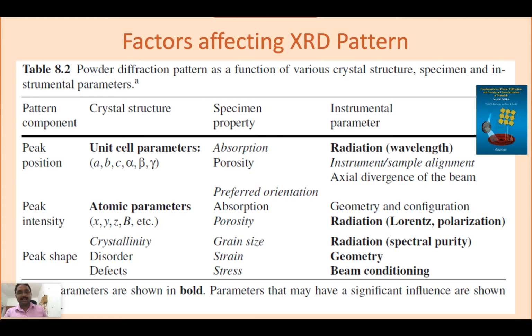But here I am telling you this table because from the table, the graph itself, we can analyze many parameters, like what is the degree of crystallinity of the sample. I can see about peak intensity. Then what about peak shape? It is not a very good shape, but it is distorted slightly. Then I can call it a very small grain sized or particle sized sample. So there will be stress in the system. It is producing not very good peaks. It is due to disorders in the system. So you can see a lot of information can be derived from X-ray diffraction itself.